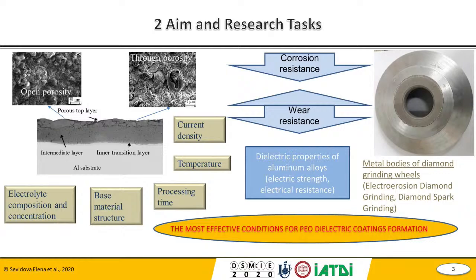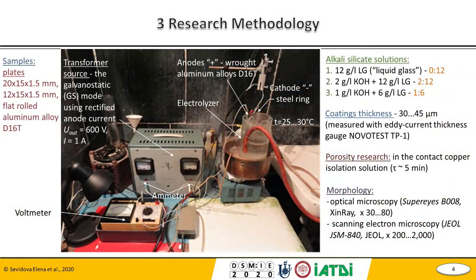And at the next slide, please, slide 4, you can see our laboratory installation for processing and formation of PEO coatings. We have used aluminium alloy flat rolled samples. We have used a transformer source under galvanostatic mode with anode current, and you can see on the right side the electrolyzer with some solution and a cathode steel ring, and the anode is our samples, aluminium alloys.